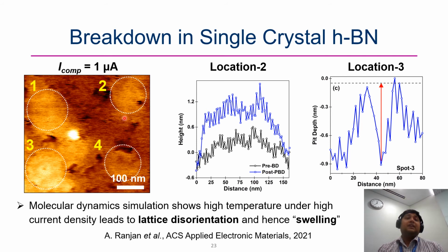What we also found is that when the current compliance is further increased, say to 1 microamp, it also starts showing swelling effects. For example, these are the 4 breakdown spots on 4 nanometer hBN subjected to a current compliance of 1 microamp. All of them show swelling at their location, and the swelling is around 1 to 2 nanometer. In many cases, we also find that a slight bit of pitting is formed as well, in addition to swelling.